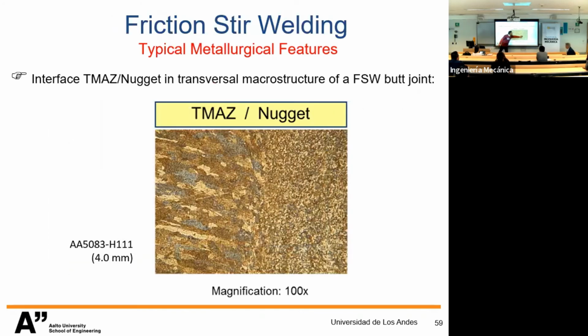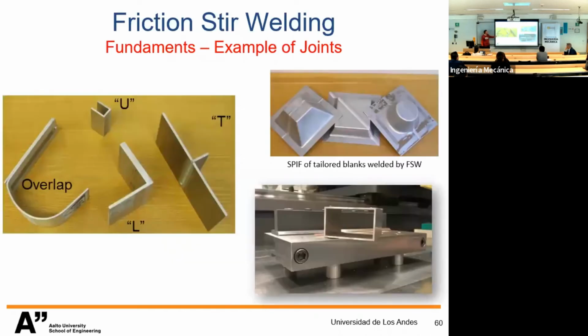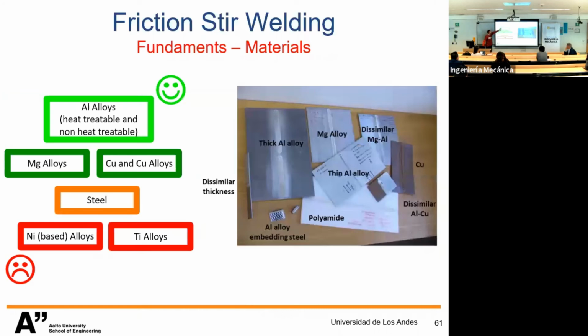You can see the stirred zone, very small grain, with dynamic recrystallization, and this is the original, similar to the original heat affected zone, but anyway, processed at a much lower temperature than the heat affected zone from the fusion process. Different joint capacities, different materials, very easy for aluminum alloys, more expensive for nickel and titanium alloys because the tool is non-consumable and the price of the tool and material has to grow as we increase the temperature of the processing. And the temperature of processing is about 70 to 80% of the melting temperature.